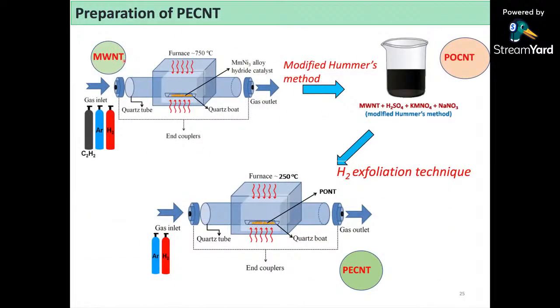So this is the furnace that I just now mentioned. Once you have done the preparation of the carbon nanotubes, one can use this modified Hummers method, where the carbon nanotubes can be treated with acids and potassium permanganate oxidizing agents, so that carefully we do that. And then use the hydrogen exfoliation technique. You can get the partially exfoliated carbon nanotubes.